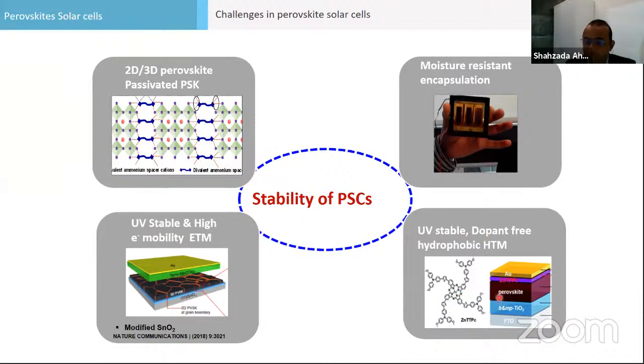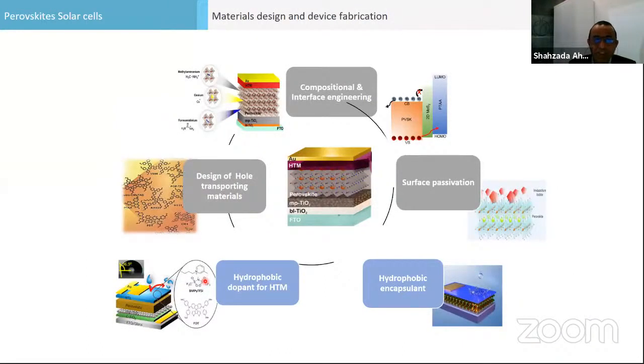A new type of p-type material, a hole transport material, which is dopant free and more stable than spiro, because spiro, which most people use, is UV unstable. And some other strategies to modify the SnO2, or putting a carbon paste on top to increase the stability. So in this direction, we adopt many procedures in our lab, like compositional and interface engineering: tuning the perovskite composition for increasing the stability and the absorption onset, surface passivation to reduce the defects, filling the grain boundaries, hydrophobic encapsulant, molecular encapsulant.